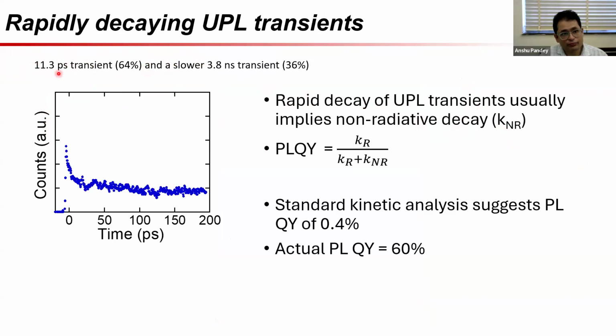Well, what is happening is, okay, first of all, what do we measure? We are seeing an 11.3 picosecond transient, which is really fast. So this is this very rapid initial decay. This actually accounts for 64% of my total signal, and a slower but not slow enough decay follows, which has a 3.8 nanosecond lifetime, and that adds up to around 36% of the sample's decay. So these are substantial. This fast decay especially is very, very substantial.